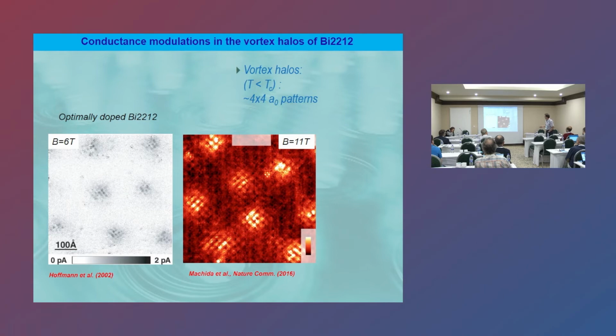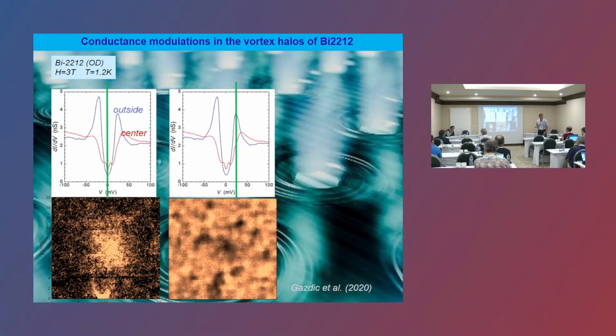So if you look at the spectroscopic signature of the vortex, this is a conductance map taken around a vortex, but imaged at an energy of 0. So this is the zero bias conductance of the vortex. You see this bright spot, meaning that the zero bias conductance increases at the center of the core. But the spectrum never showed this zero bias anomaly, which should be emerging from the background. Now, if you take the conductance map at the position of the coherence peak, the vortex appears dark, since the coherence decreases at the center of the core.